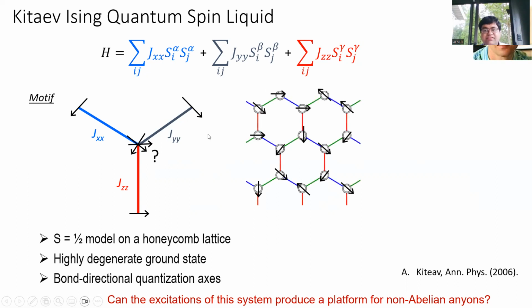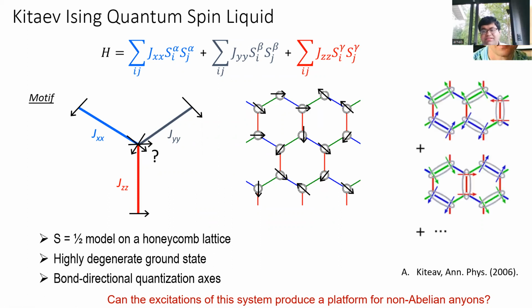Now extrapolate it to a large lattice, like a honeycomb lattice. What you find is that it is made up of a Y, an inverted Y, a Y, an inverted Y, and so on and so forth, which means that all the spins are actually frustrated. And this, as a result, leads to something called an Ising quantum spin liquid ground state, because all the bonds are Ising, and which is basically a superposition of several of these highly degenerate solutions.